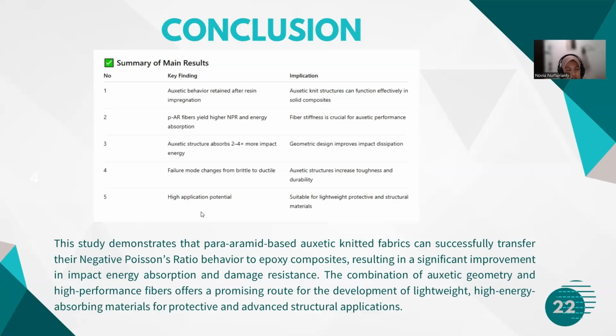This study demonstrates that para-aramid-based auxetic knit fabrics can successfully transfer the negative Poisson's ratio behavior to epoxy composites, resulting in a significant improvement in impact energy absorption and damage resistance. The combination of auxetic geometry and high-performance fibers offers a promising route for the development of lightweight, high-energy absorbing materials for protective and advanced structural application.